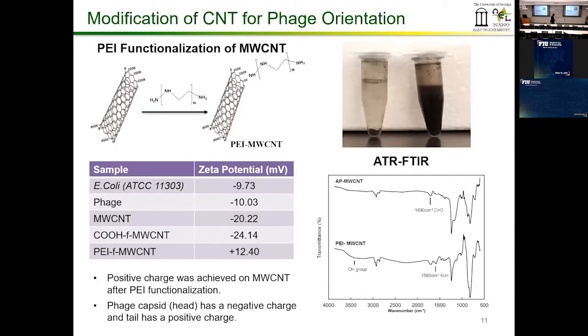So here's the methodology. You take the carbon nanotubes, you modify that with PEI. In the process, you're actually taking the potential or the surface charge of the nanotubes from a more negative charge to a more positive charge. And then because the virus and the bacteria are negatively charged, they are attracted to the positively charged surface. You can see that once you functionalize that with the PEI, the carbon nanotubes are much more dispersive and more distributed in the solution, in their true nano form.